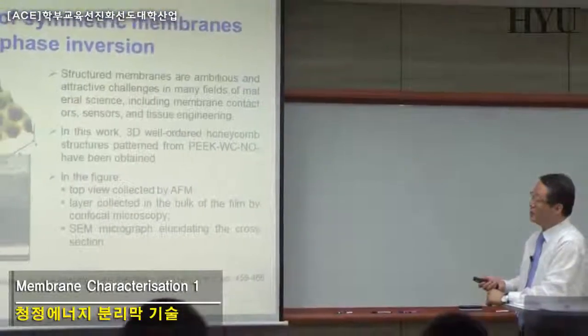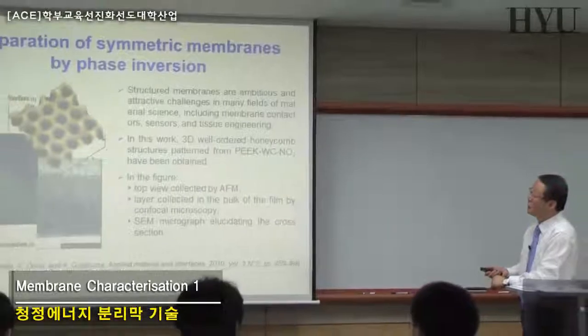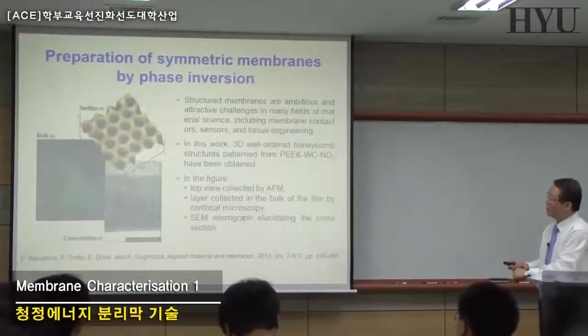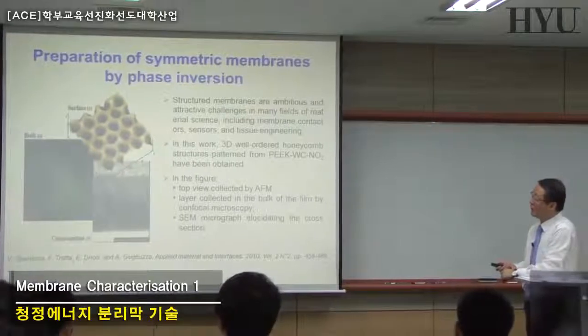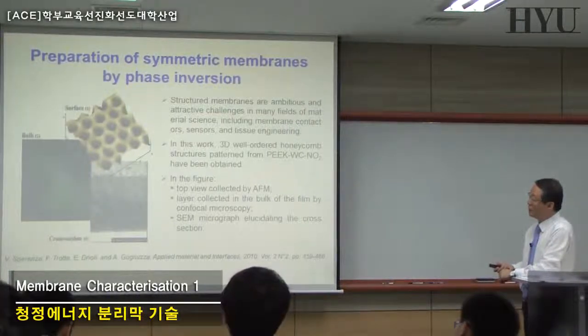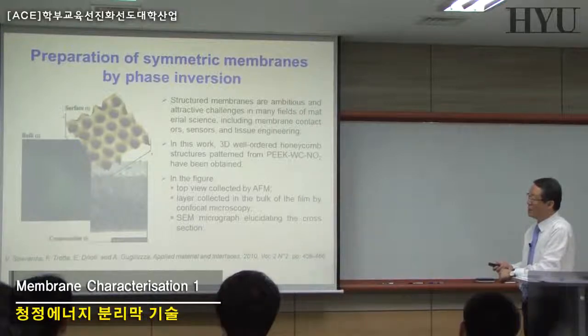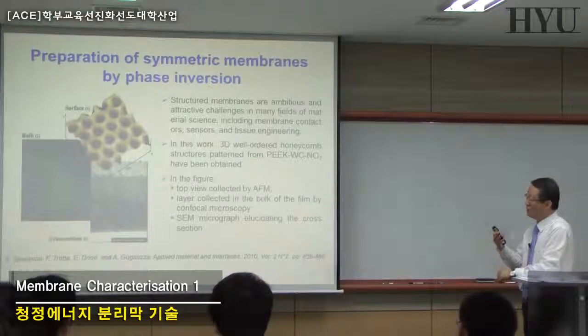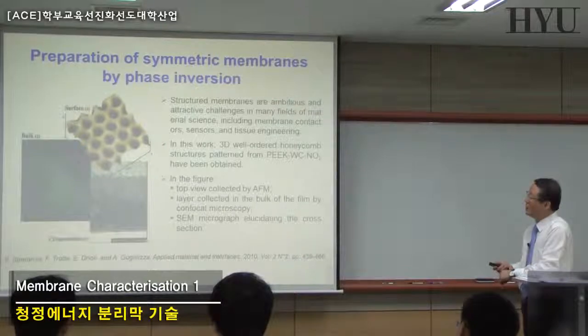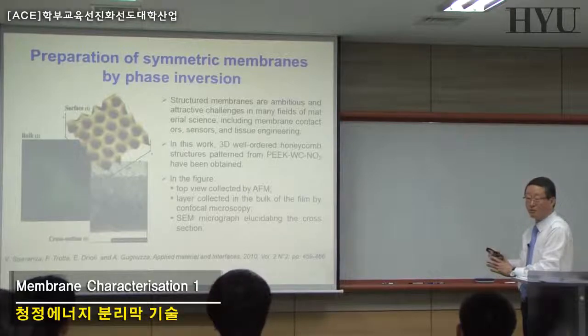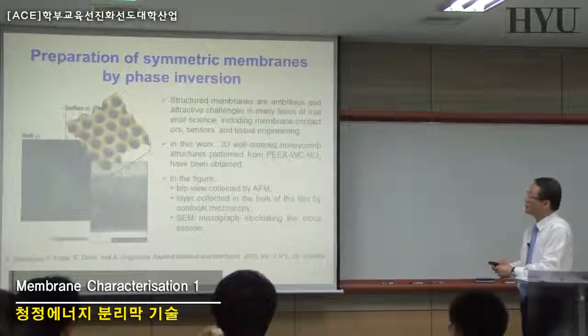So as you can see here, you have a very defined pore, particularly on the surface of the membrane. In the bulk of the membrane, it may not be the same as on the surface, but through this technique, you can make at least a very fine porous structure, at least on the surface of the membrane. You can take a look at the literature with the 3D well-ordered honeycomb structure, and not only in this paper, but you can see many other applications in the literature.